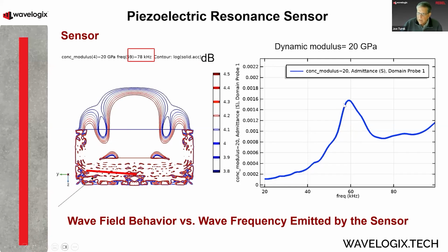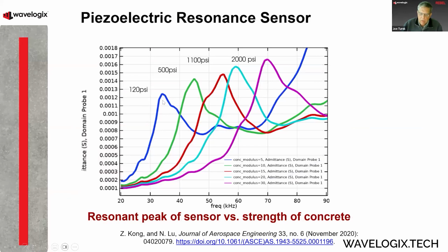Now, the cool thing is you say, well, that works great with a structure that's solid, but what happens when concrete is curing? Well, sure enough, if we embed it in concrete, as soon as there's a modulus, as soon as the concrete starts to harden enough to have some pressure, some strength, we can start to see that resonant frequency, as it cures, then changes and moves along. And these represent different PSIs, 120 PSI, 500, 1100, 2000. And we can see that that resonant frequency changes, the modulus changes as the concrete cures. And that's exactly what we would expect.